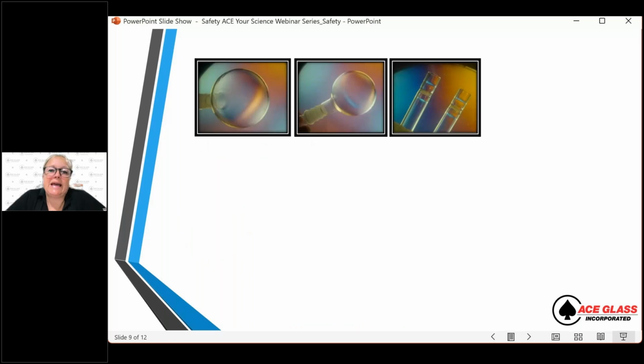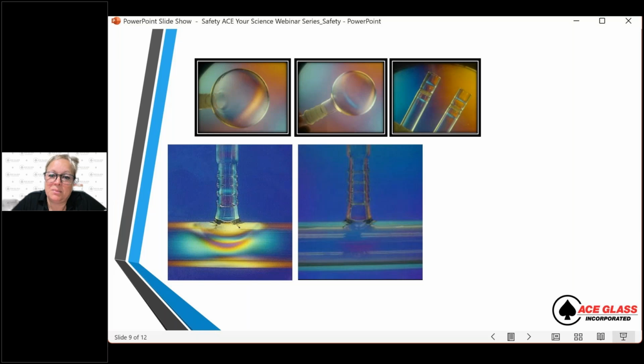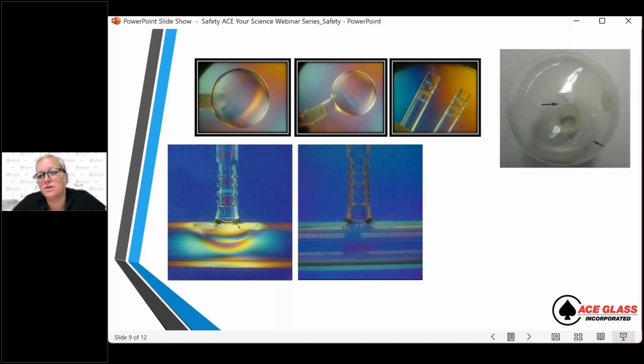So when you look at glass under a polariscope, what you want to see is, as you can see here, just nice rainbow colors, nothing that looks like a zigzag or like a flash, because that would mean that there's tension in the glass, right? If we look here, the right picture is a very relaxed glass. On the left, this is where the hose barb is attached, and there's still a lot of stress in the glassware. So ideally, we would anneal it, get the stress out of the glassware in order to relax it and avoid potential accidents in the future.